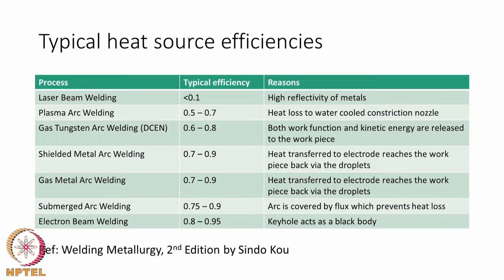And when it comes to the rest of the arc welding processes, normally you do have a good value between 0.6 and 0.9, going from GTAW in the electronegative mode to shielded metal arc welding and gas metal arc welding. The reason why in the electronegative mode we do have a higher efficiency is for two reasons. One is the kinetic energy of the electrons being absorbed by the material. The electrons that are accelerated towards the base material are stopped suddenly, and all the kinetic energy is left to the base material, which converts it into heat, and that is one reason. Another reason also is the work function.